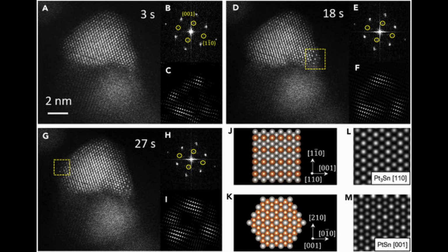Dehydrogenation is considered a structure-insensitive reaction, meaning that a very small group or even single platinum atoms can catalyze the reaction. On the other hand, side reactions such as coking and hydrogenolysis are structure sensitive and require relatively large ensembles of platinum.